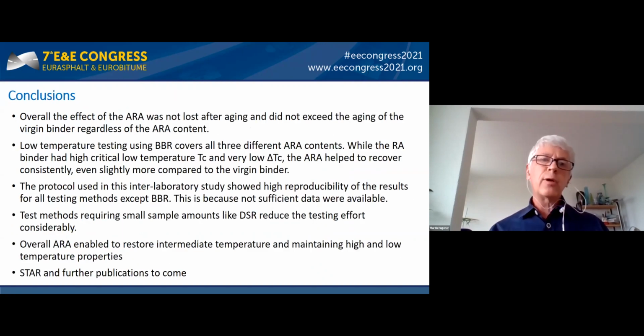So the conclusion overall: the effect of the ARA was not lost after aging, and this did not exceed the aging of the virgin binder, independent of the ARA content and also independent of the temperature range, low temperature, intermediate temperature, or high temperature. So actually the protocol we used in this interlaboratory study showed quite high reproducibility, unless we didn't have enough results. So that's why we are now working on a RILEM recommendation for the evaluation of ARA blends in hot mix asphalt.